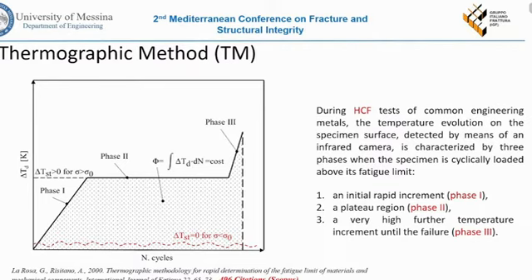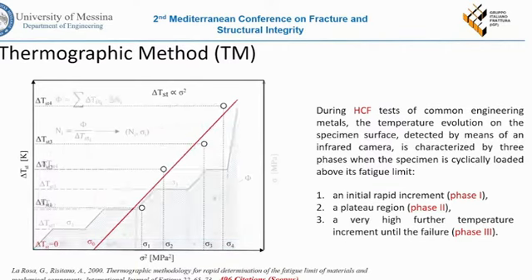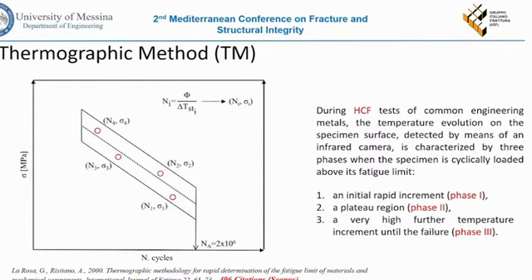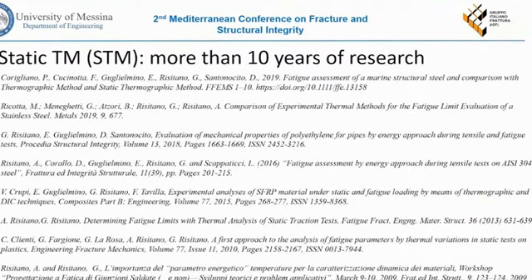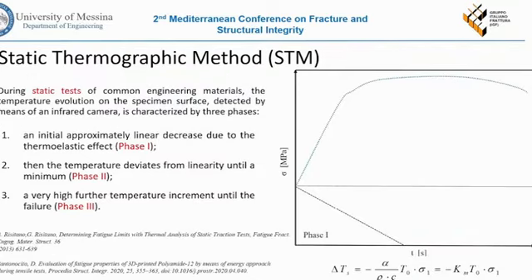So, according to the Risitano thermographic method, we can assess in a rapid way the fatigue behavior of engineering materials, both metals and polymers, by measuring the thermal trend of the specimens stressed above their fatigue limits. So we can obtain information on the fatigue limit and on the overall SN curve. A new infrared thermography application is the adoption of the static thermographic method, according to which during a static tensile test, we have 3 different phases in the temperature trend.